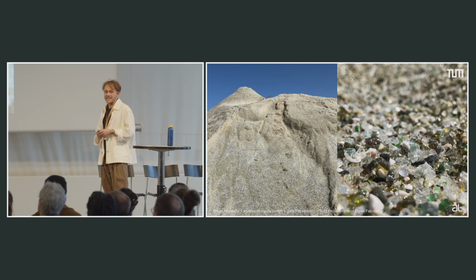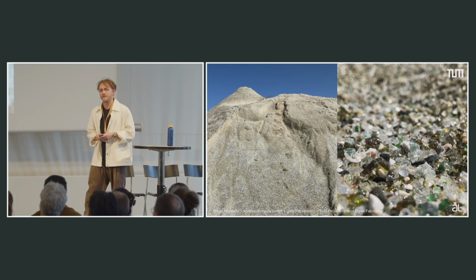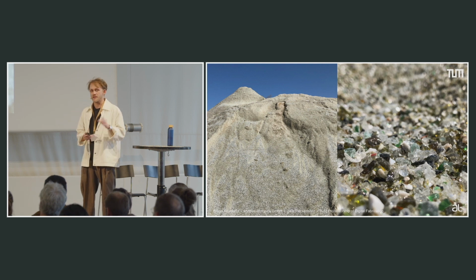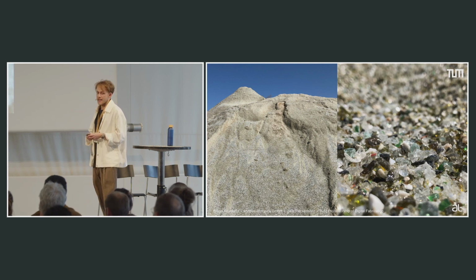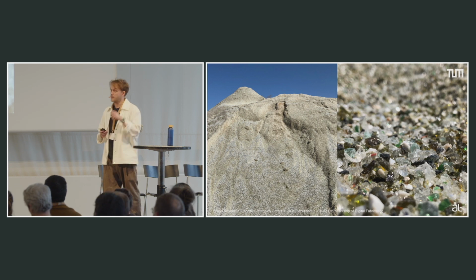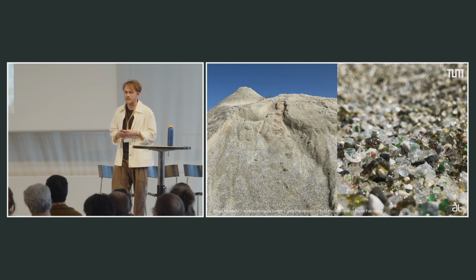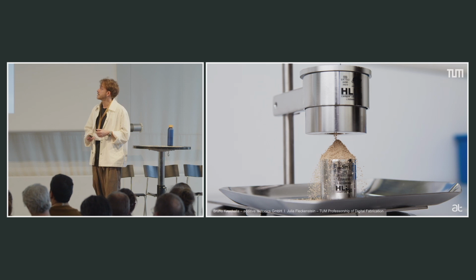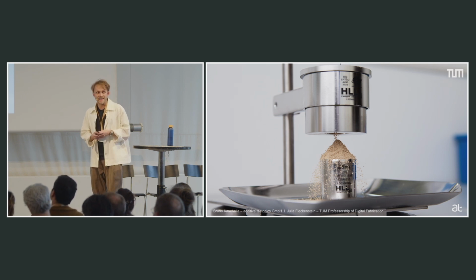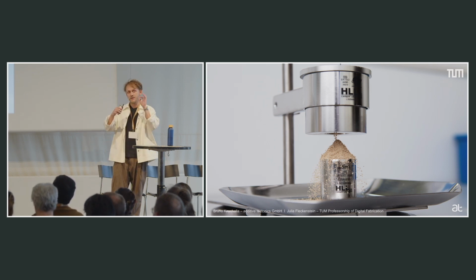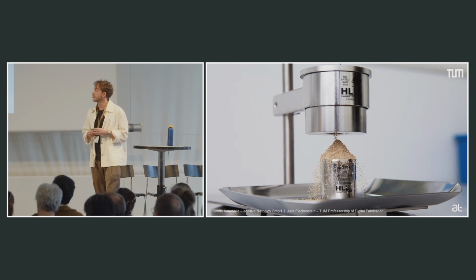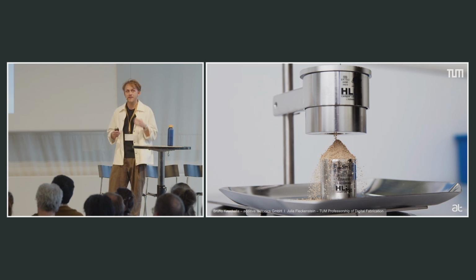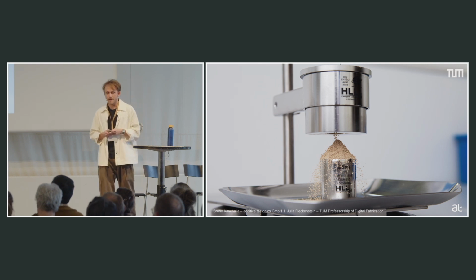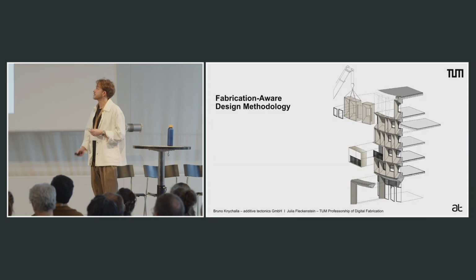We used recycled glass as aggregates from bottles from a local provider, just 5 kilometers away from my company, and 70% of the volume inside this material is basically this aggregate. These recycled bottles get expanded and granulated into different sized spheres, and we need these different sizes to generate a nice packing density. And then the Portland cement is added, and also cellulose.